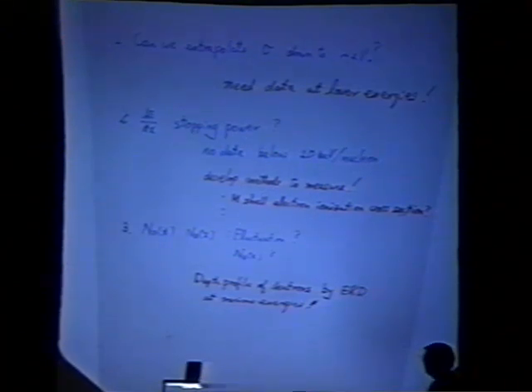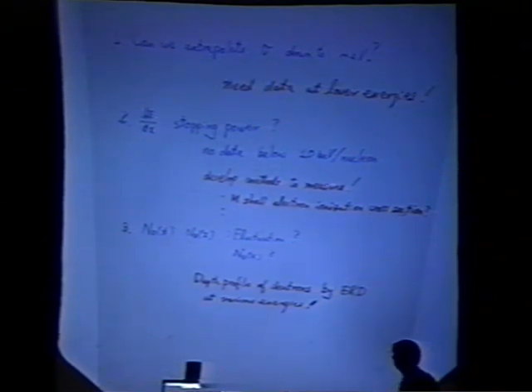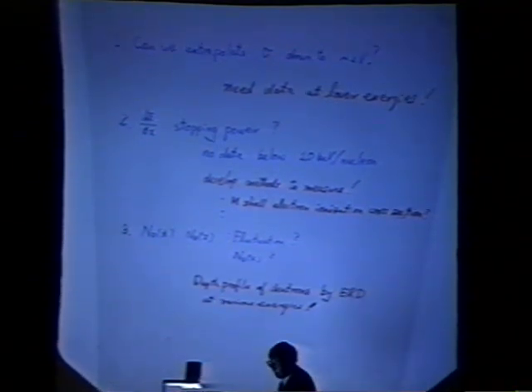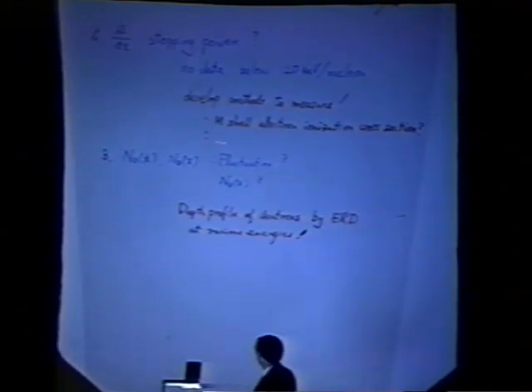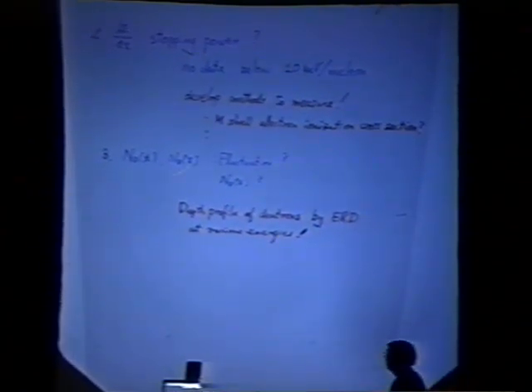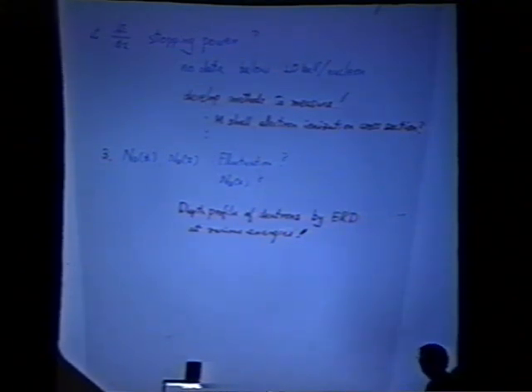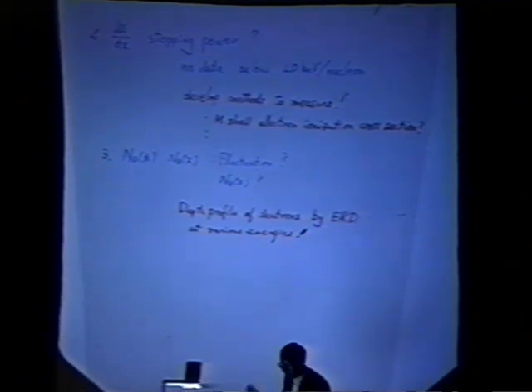And we are thinking of several ways. One of them is to measure the M-shell electron ionization cross-section and so on. And also we need the target deuteron density. Of course, there is not so much fluctuation, but there is a fluctuation. So we have to develop the technique to know the target density during the bombardment. To do that, we are planning to measure the depth profile of deuterons by so-called elastic recoil detection at various energies. Thank you very much.